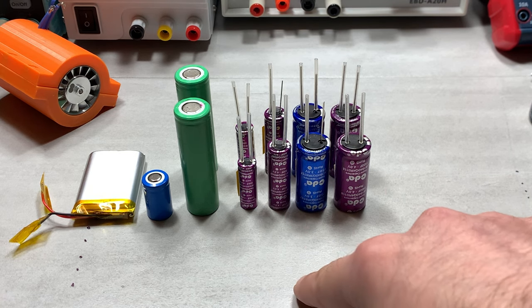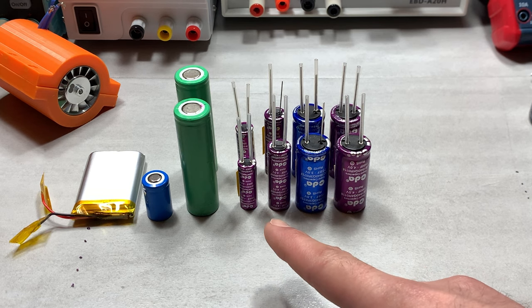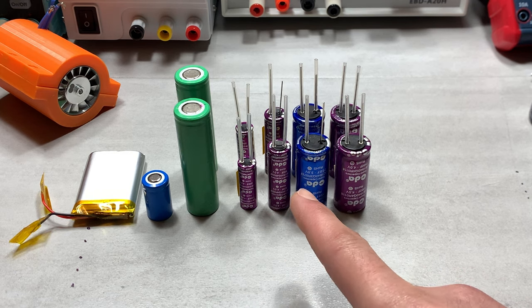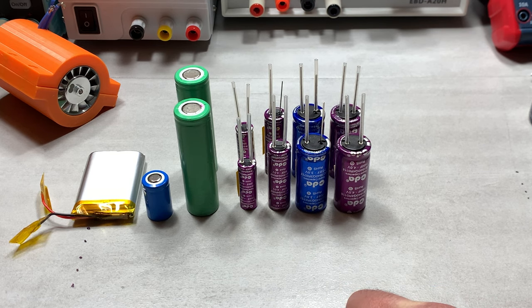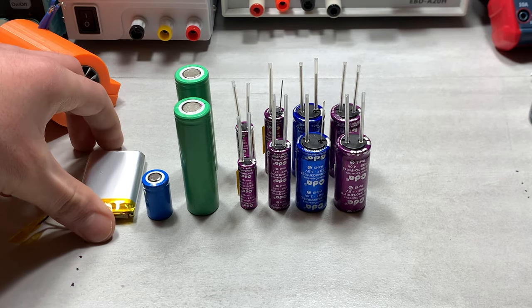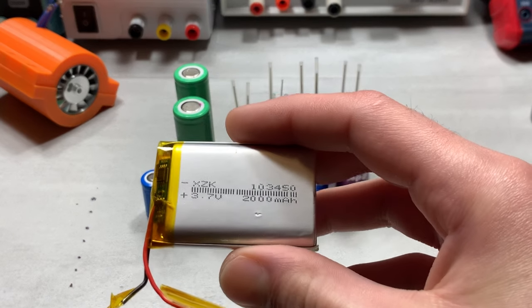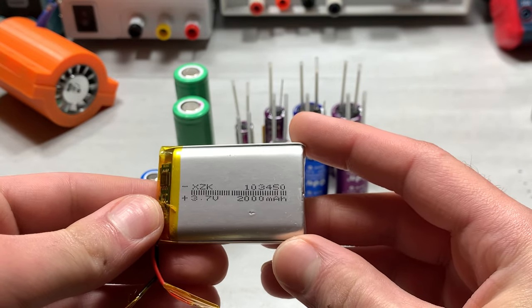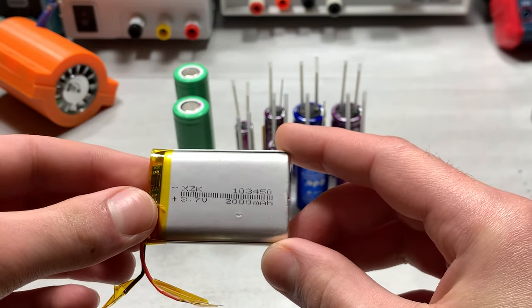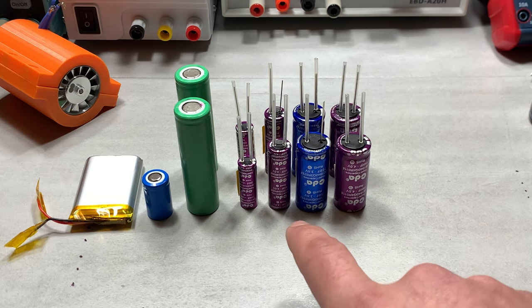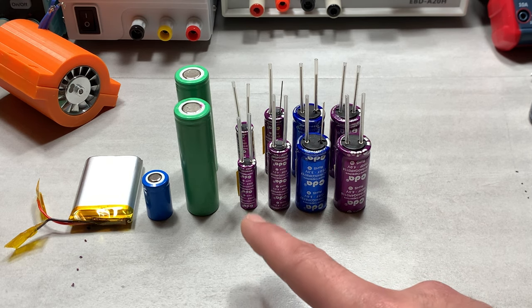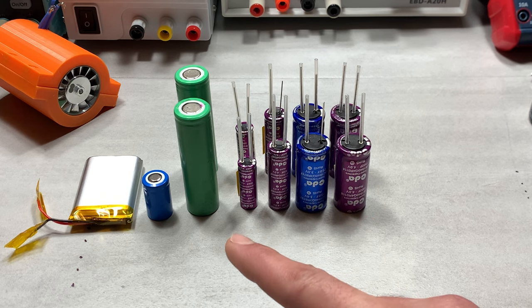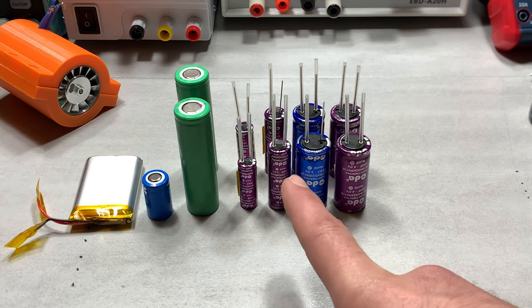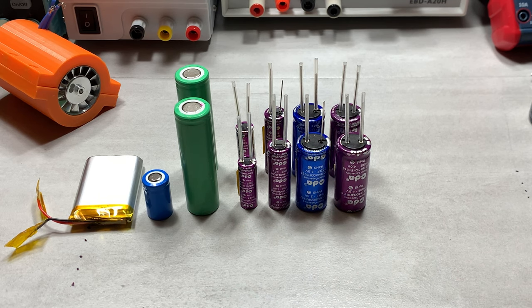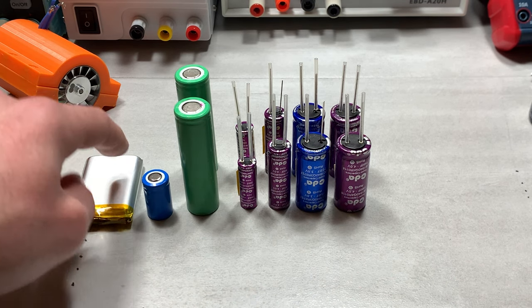So the manufacturer was actually kind enough to provide a milliamp hour equivalent rating, because these do have very similar nominal voltages to that of a standard lithium battery. Of course, a lithium ion battery has a nominal voltage of 3.7 volts. However, the fully charged voltage of a lithium battery tends to be up to about 4.2 volts. So again, the manufacturer has provided a milliamp hour equivalent rating for each of these cells, which will make it very easy for us to determine the relative C rating of each of these cells, and will really put into contrast the discharge and charge rates of these batteries.